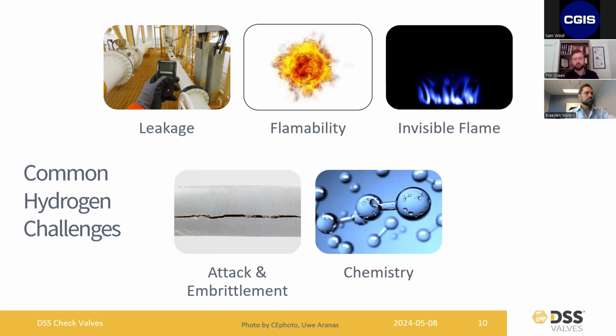Also, hydrogen embrittlement is another concern. So hydrogen is known to react with specific materials and also cause failures, can form cracks, makes the material brittle, and especially in high pressure environments is very dangerous. So one of the things that we've learned is that there's several materials that have been out there for a while, but 300 series stainless steels, austenitic stainless steels, are some of the most effective materials to be used with